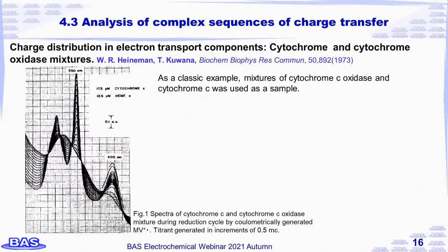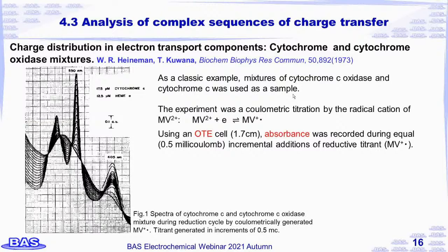The third example is analysis of complex order of charge transfer using the optically transparent electrode method. As a classic example, a mixture of cytochrome c oxidase and cytochrome c was used as a sample. The experiment was a coulometric titration by the radical cation of methylviologen. Absorbance was recorded during equal incremental addition of reductive titrant. The intensity of the 605 nanometer band of the oxidase changes during the initial and final portions of the titration. The intensity of the 550 nanometer band of cytochrome c changes predominantly during the intermediate stages.